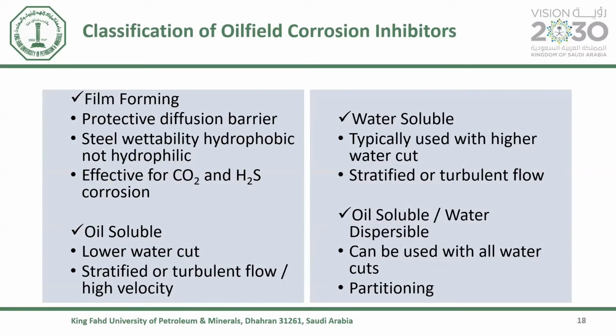So in the oil and gas industry, corrosion inhibitors are classified into film forming, oil soluble, water soluble, oil soluble and water dispersible. So all these classes are classified based on their application. For example, film forming, they will form a film on the surface and they will wet the surface and form hydrophobic layer on the surface, mainly effective for CO2 and H2S corrosion.